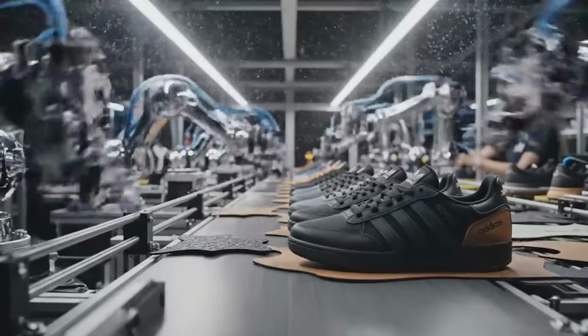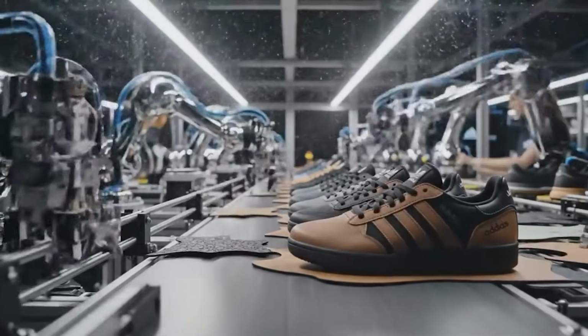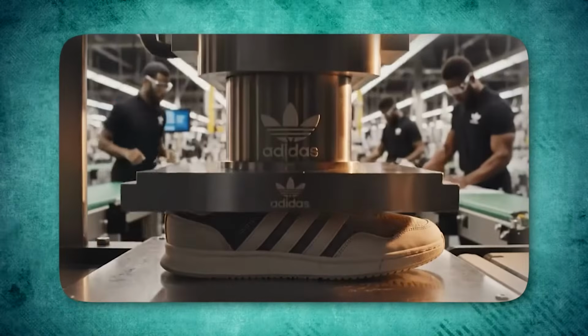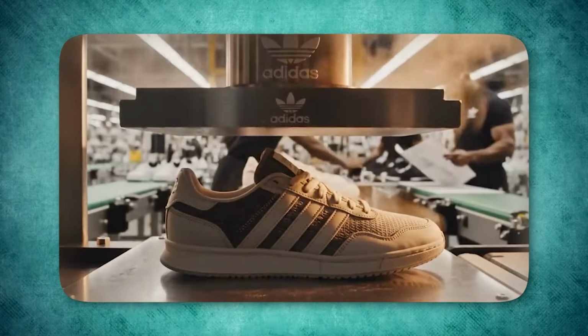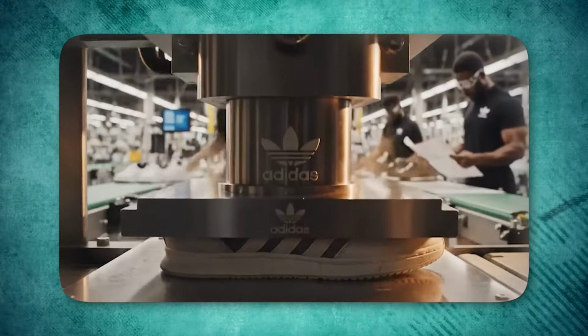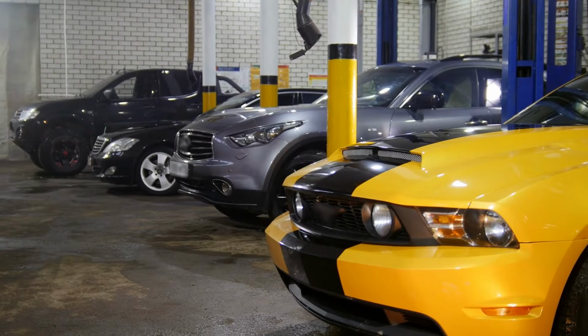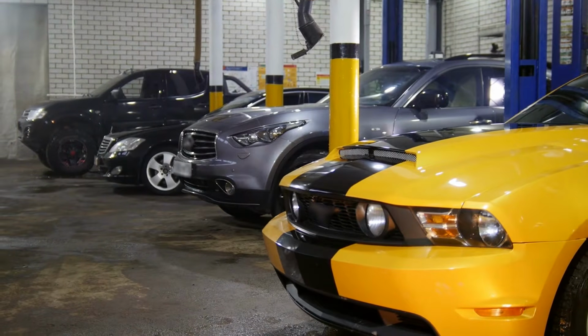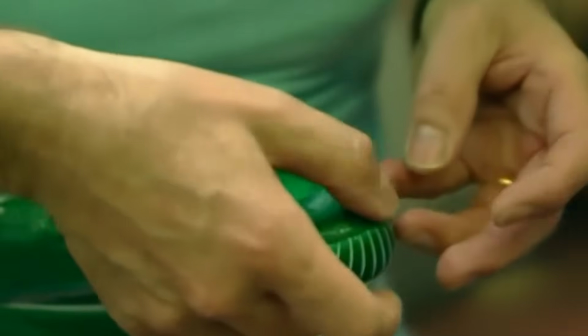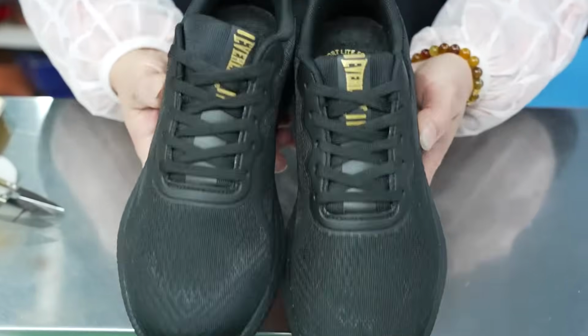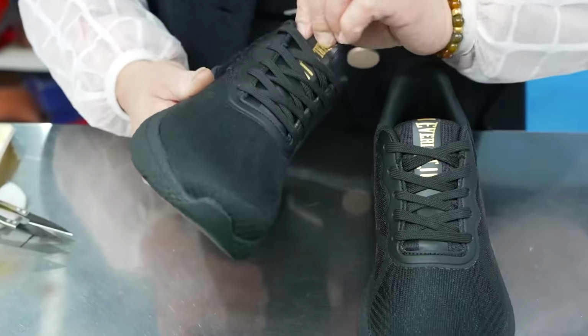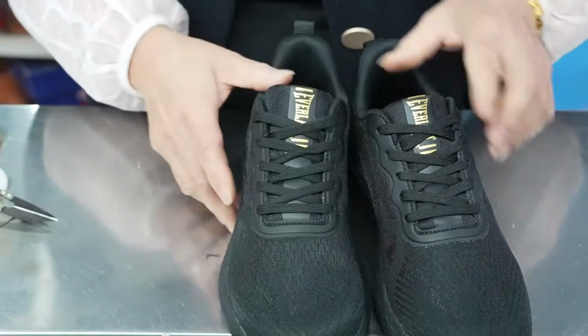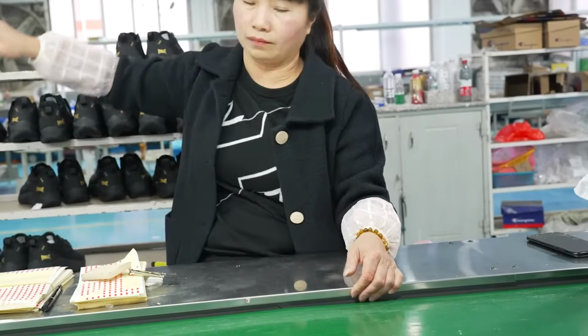Once the EVA reaches the right consistency, it gets injected into a metal mold at pressures ranging from 600 to 800 kilograms per square centimeter. For perspective, that's roughly equivalent to the weight of a small car pressing down on every square centimeter of the mold. At some facilities, like the ones producing premium performance shoes, the pressure can reach as high as 1,200 bar. This extreme pressure forces the molten EVA into every tiny detail of the mold cavity, ensuring consistent density and perfect replication of the sole design.